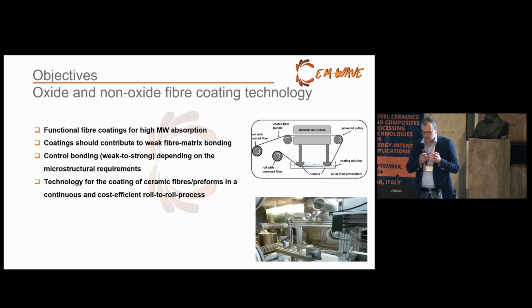So everybody knows, if you want to reinforce silicon carbide by a silicon carbide fiber and you have no interface, it's just a monolithic and a bad monolithic ceramic. So the interface is very important. The interface most of the time fulfills not only one task, but several tasks. Maybe the coating has a function especially for microwave absorption when you do some microwave assisted CVI, but with the coating you can also have an influence on the fiber matrix bonding, how stiff or how weak this bonding is, and this is a challenge.